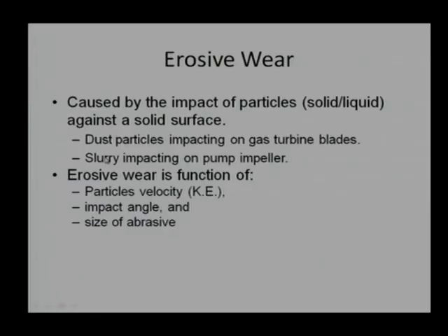If I am able to divert the particles and bring the velocity to zero kinetic energy, there will not be any wear rate, at least from the erosion wear mechanism point of view. There are a couple of examples which are very common. When a helicopter passes through dust at a height of maybe 1 to 2 kilometers, where there is too much dust, then what will happen in that case? Dust particles will impact the gas turbine blades and cause erosive wear.